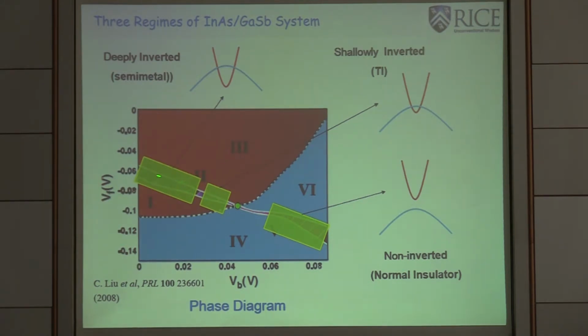Now, if the density is much higher than this, you never get an energy gap. Actually, you always see semi-metal behavior. So you have to push this into relatively low density, 1 × 10^11. Then if you use the gate, you can push down to this point. This point is the critical point between the inverted and non-inverted. Sometimes we call it the touching point, which means these two band edges will couple to each other. Now, if we disregard the interaction, we will think this is the region for topological insulator and this is the region for the semiconductor.